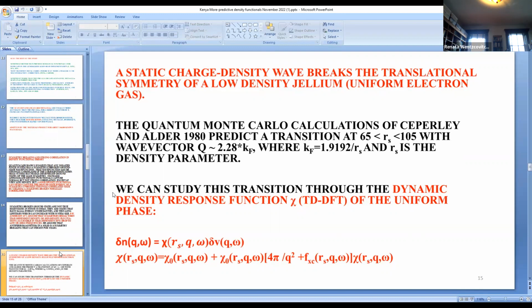RS is a density parameter. RS is roughly the average distance between electrons in the atomic units of Bohrs. So these are obviously very low densities. He also predicted that the wave vector was about 2.28 times the Fermi wave vector, which is a constant over RS.